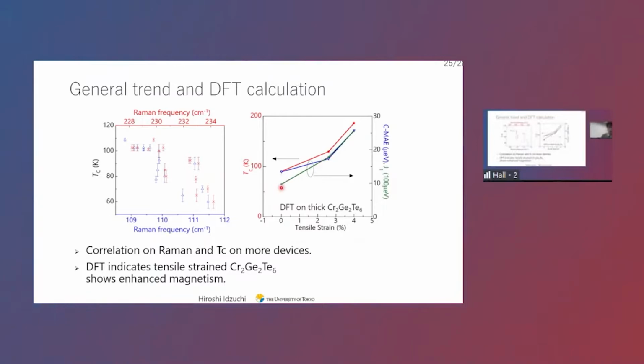Yes. We also looked at other systems, but in this case the chromium distance is very far away, so it typically would not be much affected under tensile strain, but the other would contribute to it. So you may want to look into it. And you only attribute it to tensile strain, but since you have nickel oxide, the antiferromagnet, there is a ferromagnet-antiferromagnet coupling. So it's like a magnetic proximity effect that also plays a role here in enhancing the Tc and other magnetic properties.